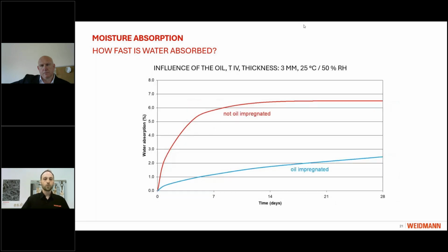The oiling is quite drastic. So here you can see a 3 millimeter board at ambient conditions like before. And you can see that when we do not oil impregnate it, we have some 7 to 14 days to reach equilibrium condition. Whereas even after 28 days, we are far away from this point. So the oil really hinders, especially also the diffusion, because many of the spaces the water wants to go through and wiggle around are already occupied, in a way, not with the same attachment points.